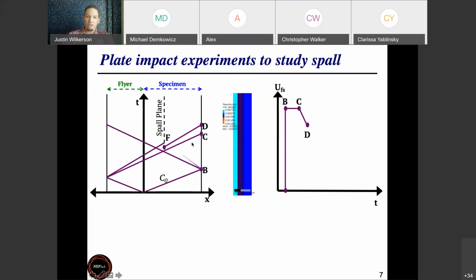Okay, but before that wave goes all the way to the back surface, there's actually another interaction in the spall plane. So I have a release wave coming from the left. In addition to that, I have a release wave coming from the right, which is coming from the back face of the target plate. And those two release waves are coming to each other right in the middle of the specimen, which is where I'm going to form the spall plane. So I have a release wave that's trying to take me from a highly compressed state down to zero stress, coming from the left. And then I have another release wave coming from the right that's trying to take me from a highly compressed state back to zero stress. And when those two collide, they essentially release each other and they take you into a tensile state. And so rather than going to zero stress, you actually go to a highly tensile stress state. And that's where we get all of our damage in the material.